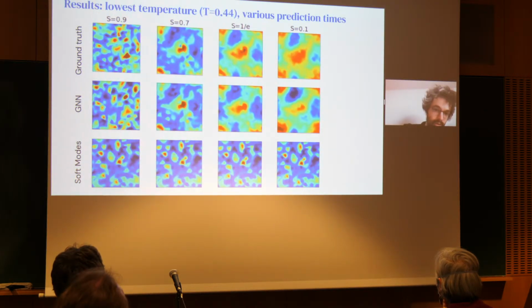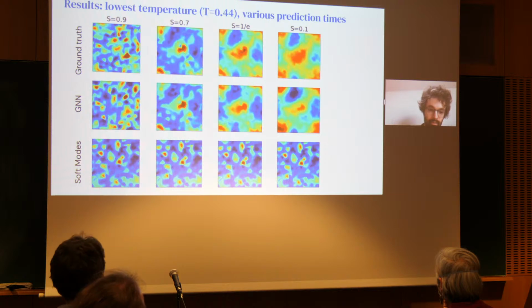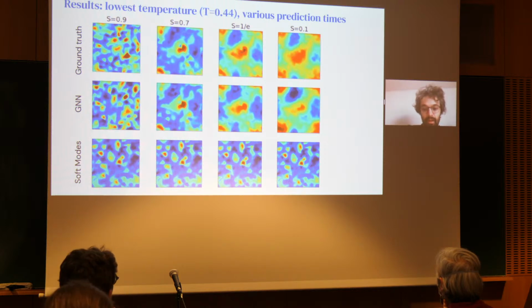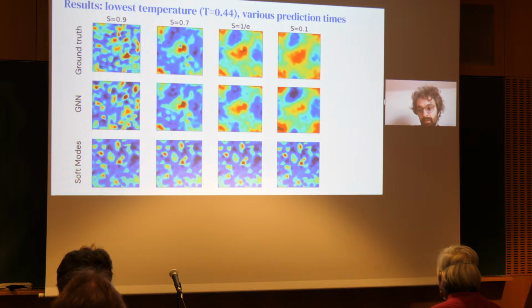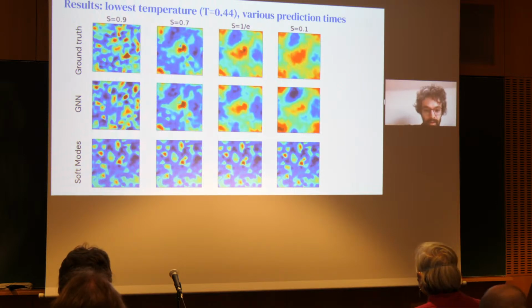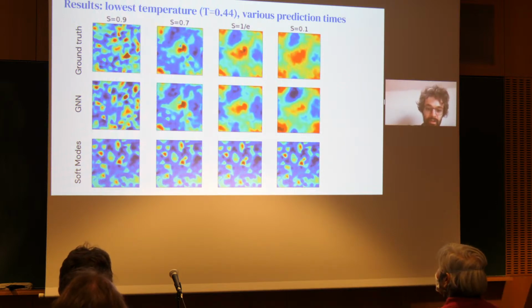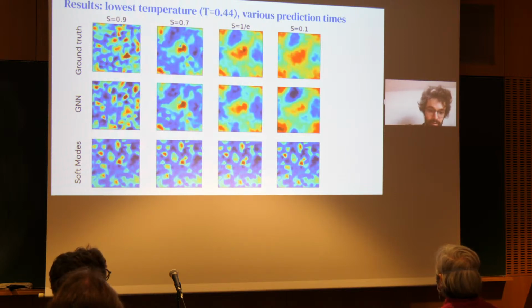And so this was showing a comparison between the ground truth at the top, the model in the middle, and then the soft modes, which is this baseline, at the bottom. The soft mode doesn't have a time scale, of course, so it always makes the same prediction, which is why you would expect that it only does well at a particular time. And this is showing at which time this is occurring. So this is corresponding to the first or second column.